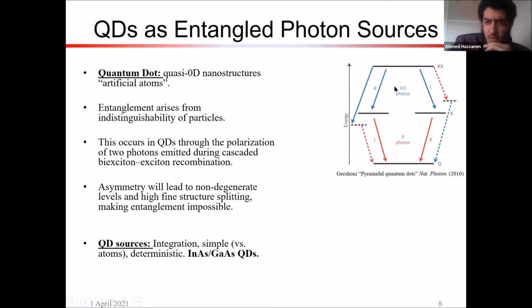And so what you can see here is that if the bi-exciton is going to relax into the exciton, and these two intermediate levels are different, then you're going to get emission of different photons with different energies, and so they're not going to be indistinguishable. So it's going to be really hard to create this entanglement. And so this asymmetry in quantum dots can really kill their ability to create entangled photon sources, or entangled photons rather. And so what we want in our quantum dots is for them to be very symmetric.